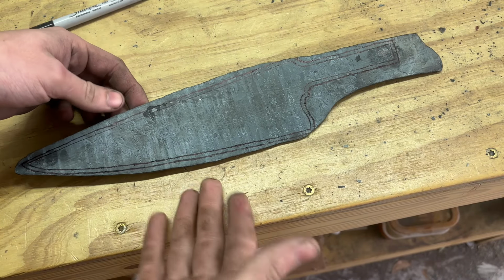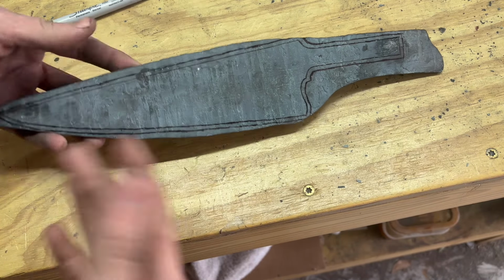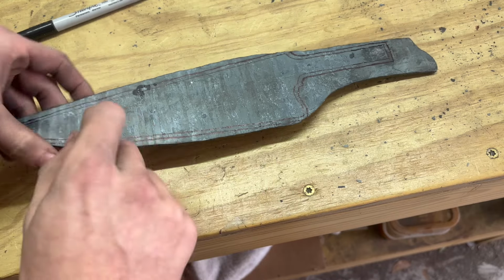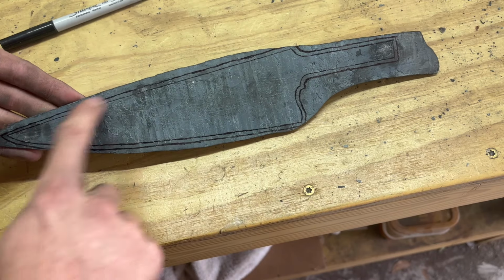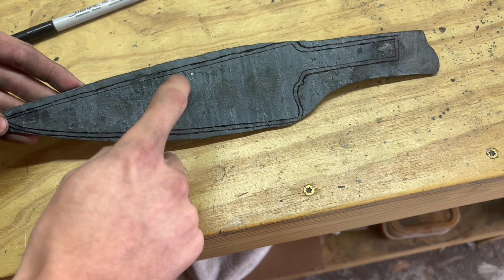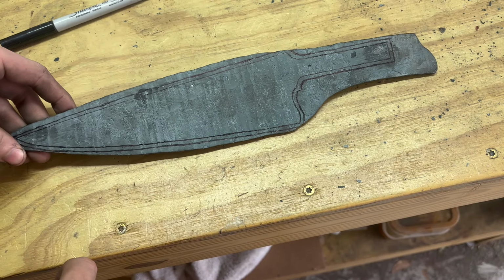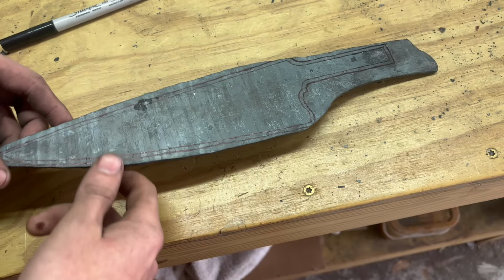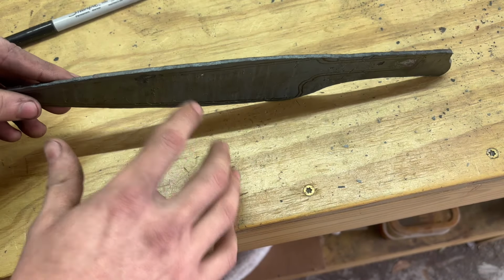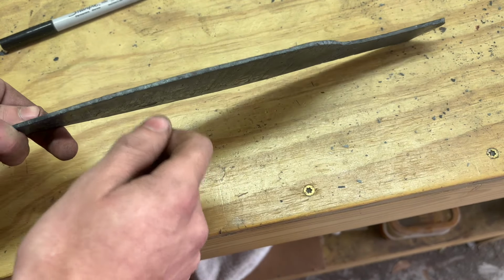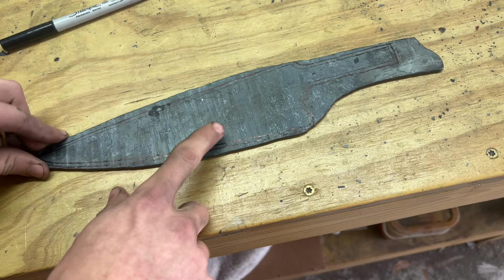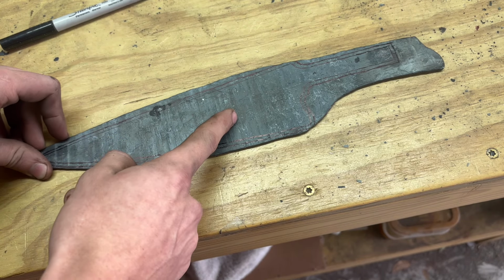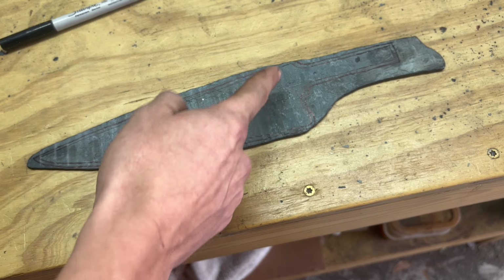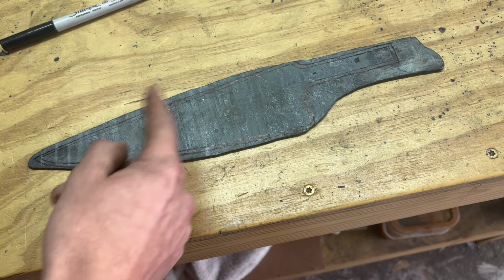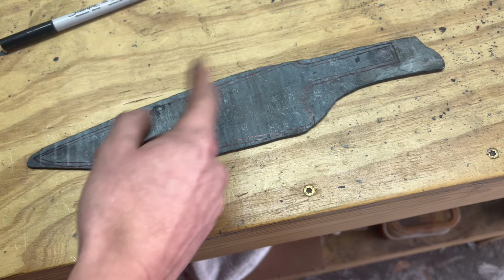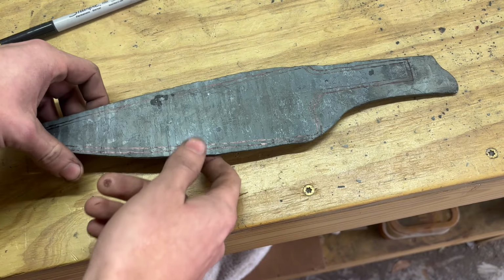You can see I didn't forge very closely to shape, which I've said before I do because I want to be able to draw on the exact shape of the knife that I want to make, and that's what I've done. Also for San Mai, it's extremely important for the pattern that the core steel, in this case the 80CRV2, is perfectly centered between the two pieces of the cladding steel, here 15N20.